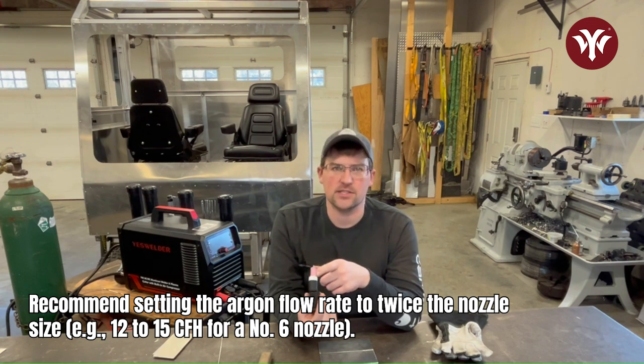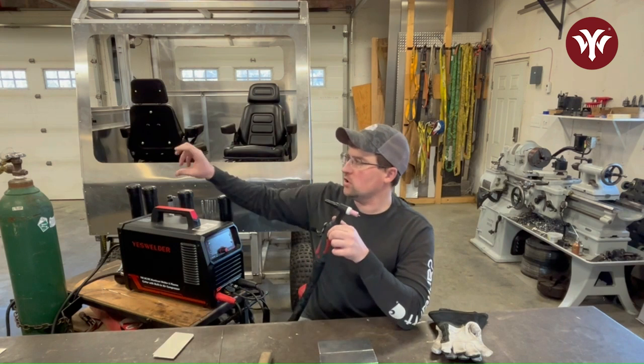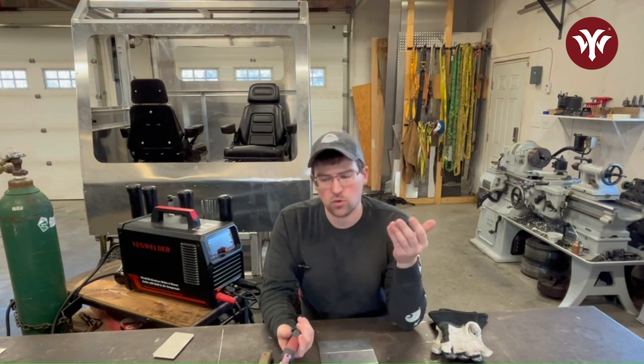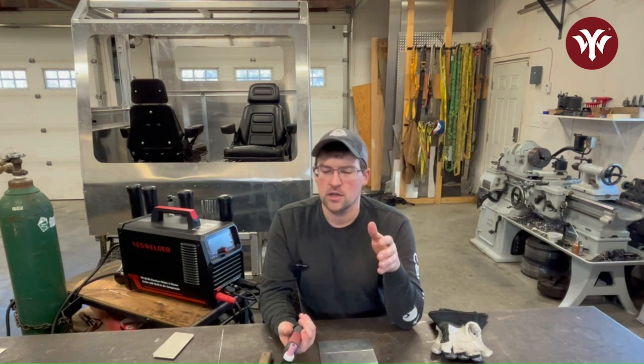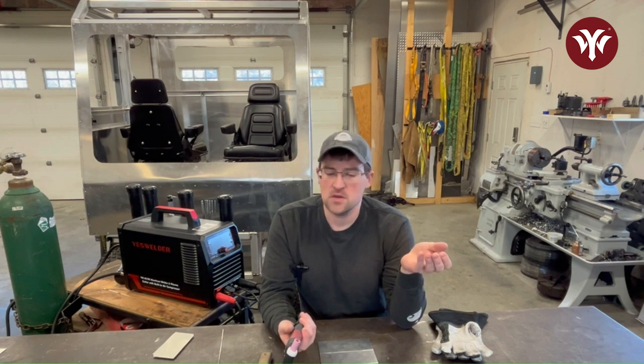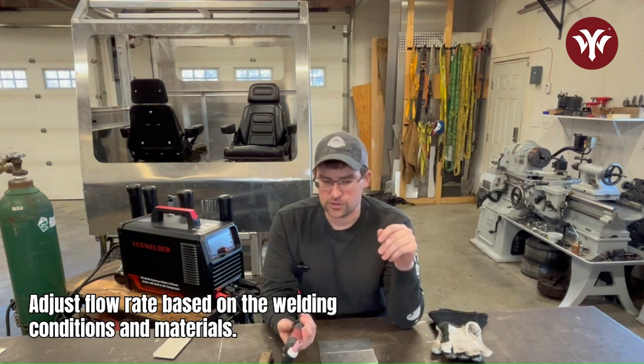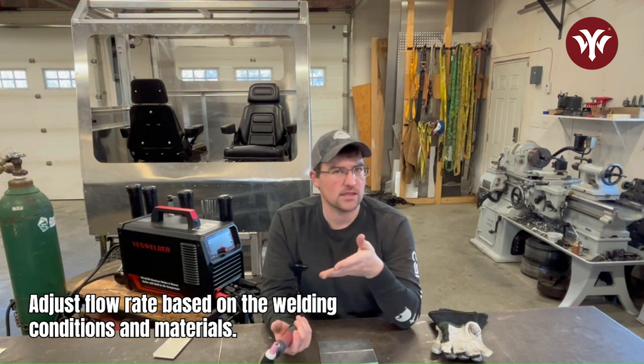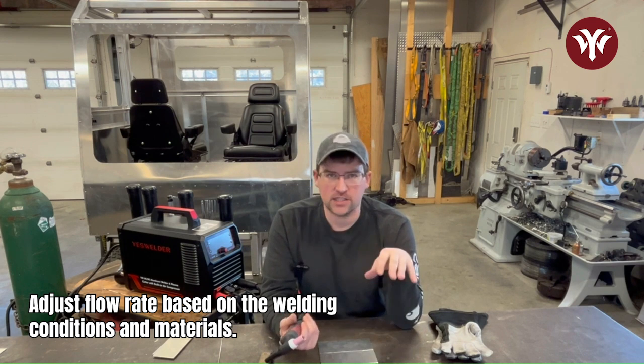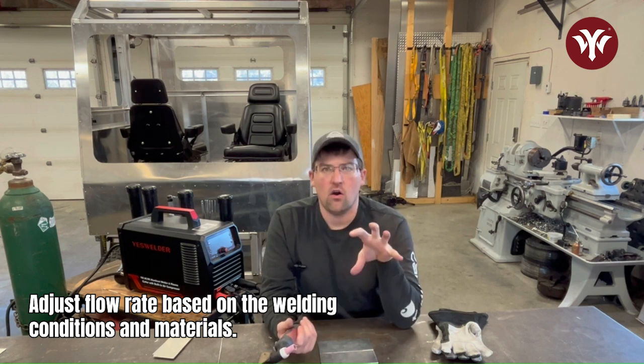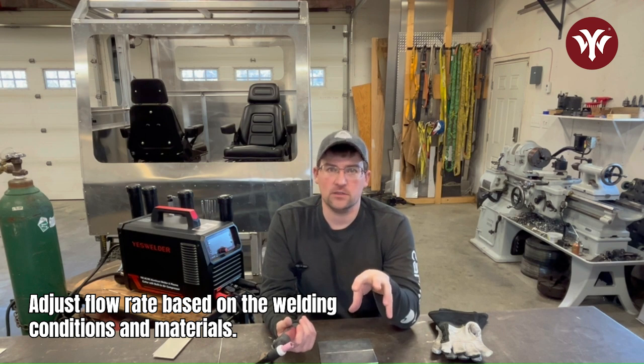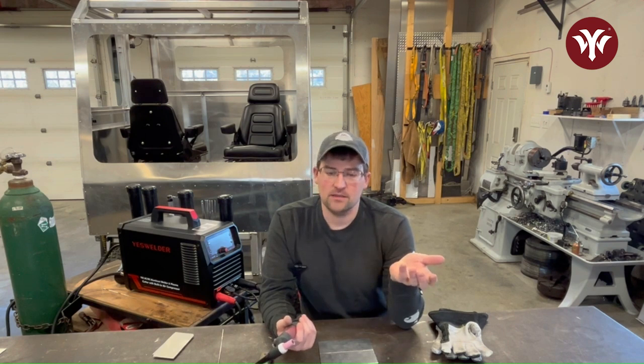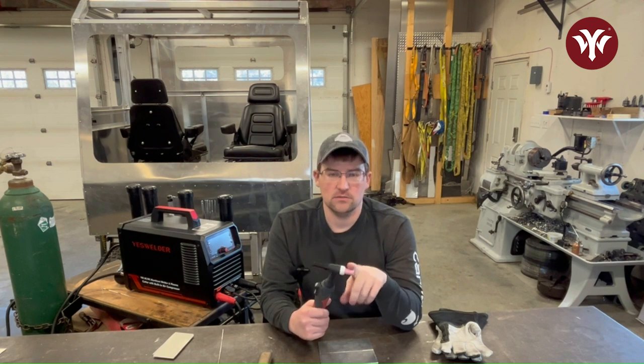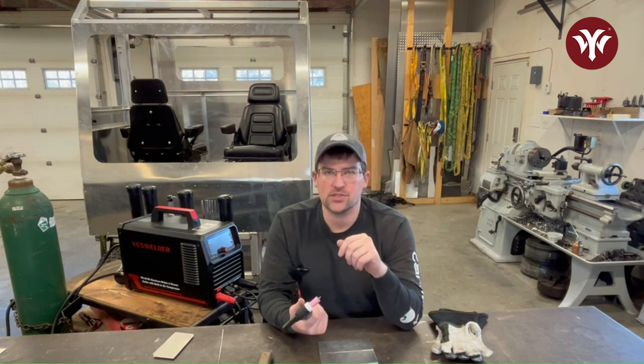So if we're using a number 6 nozzle, we're going to dial our argon flow into about 12 to 15 CFH. If you're using a smaller nozzle, you need less gas flow. If you're using a large Pyrex cup welding stainless, you're going to need a ton of gas flow to cover all of that metal and the weld puddle. So again, 2 times your nozzle size is a good place to start.